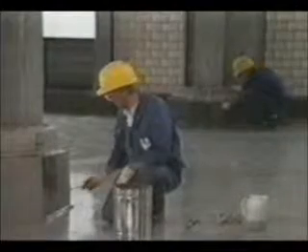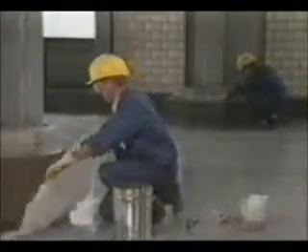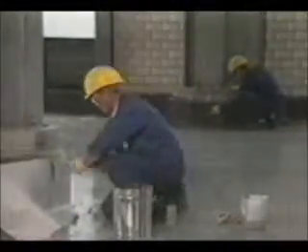On the ground floor of the plant, the coating system acts as a secondary containment. This measure works as a barrier to any leaks and spills, in accordance with Germany's legislation on the protection of water resources. The coating system is applied on the walls first, in the same sequence as on the floor itself. Before the carbon fiber matting is laid, earthing tape is embedded at regular intervals in the laminate layer.